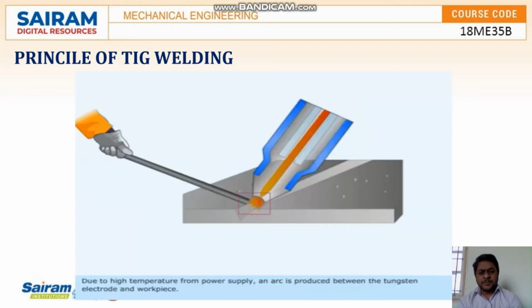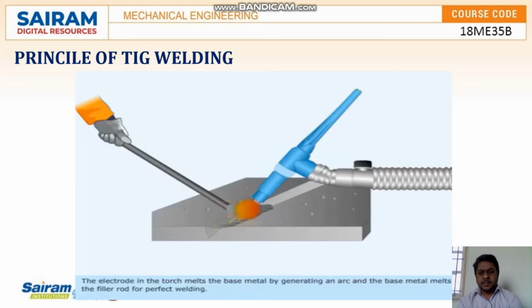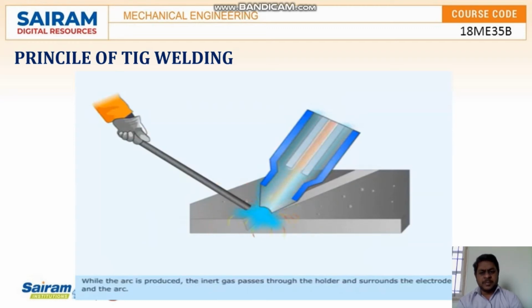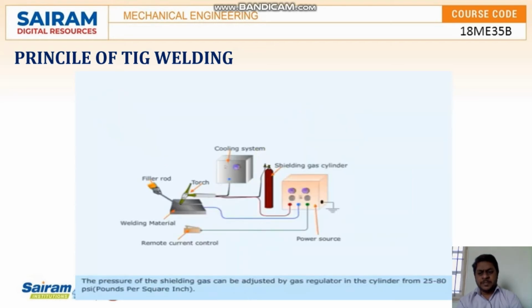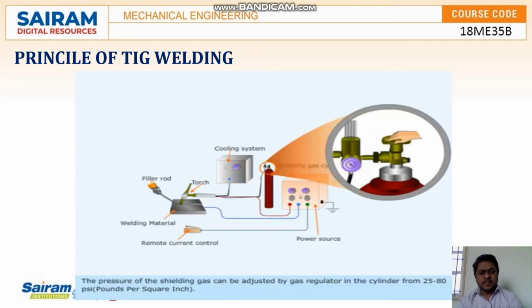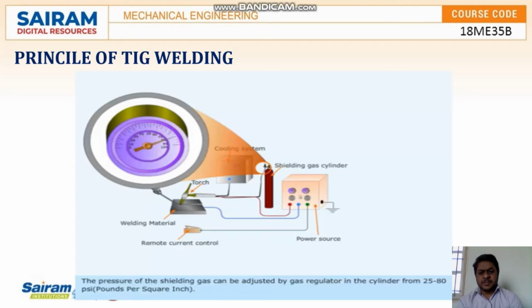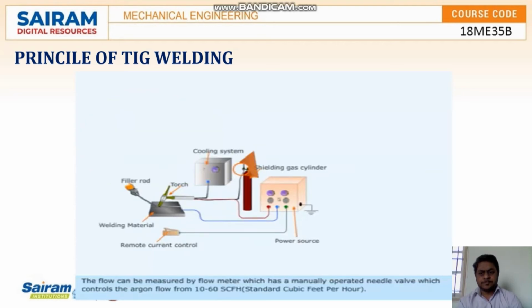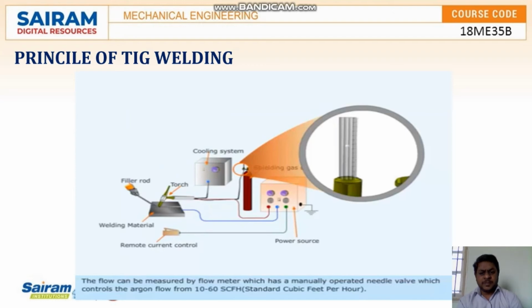Due to high temperature from the power supply, an arc is produced between the tungsten electrode and workpiece. The electrode in the torch melts the base metal by generating an arc, and the base metal melts the filler rod for perfect welding. While the arc is produced, the inert gas passes through the holder and surrounds the electrode and the arc. The pressure of the shielding gas can be adjusted by the gas regulator in the cylinder from 25 to 80 pounds per square inch (psi). The flow can be measured by a flow meter, which has a manually operated needle valve that controls the argon flow from 10 to 60 standard cubic feet per hour.